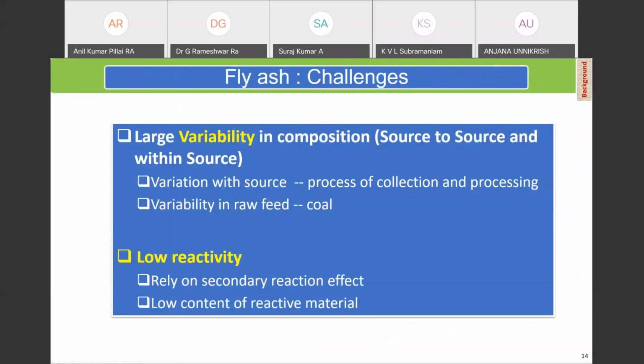But one of the challenges we have with fly ash as it is produced in India is the large variability. We have a very large variability in composition. I'll show this in the next few slides. There's a large variation from source to source. So if I collect fly ash from 3 different power plants, I'll get very different reactivities. I'll get very different compositions. The variability in the raw feed, even if I look at the same source, because the coal that is burnt is different, keeps changing. Even from the same source, the fly ash is not of a consistent quality or of a consistent composition. So that makes using this fly ash a little bit of a challenge.